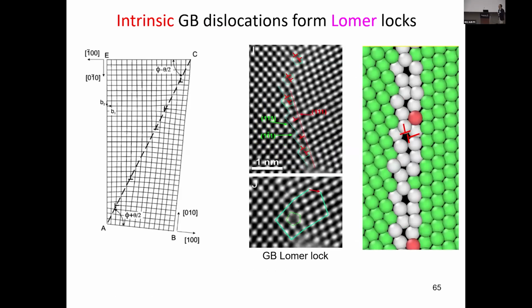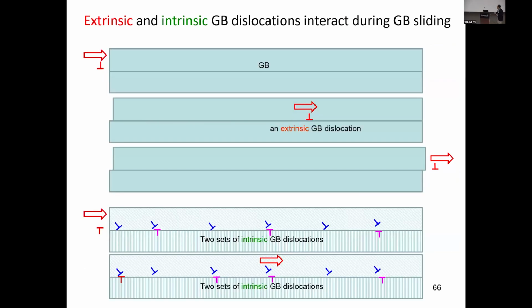And for these two types of intrinsic grain boundary dislocations, we can also conduct atomistic simulation to study their initial structure and also their evolution under the load. And these intrinsic grain boundary dislocations can also impact, for example, the sliding or the coupled sliding or migration at the grain boundary, because to produce the grain boundary deformation, we need an extrinsic grain boundary dislocation, as indicated by this red symbol, right?